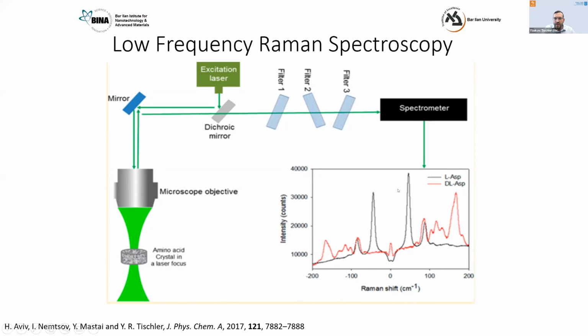For example, the L has this peak around 50 wave numbers, which is completely absent from the racemic mixture. And the way we understand that intuitively, we did some analysis as well, is that if you look at a chiral crystal, if it's entirely L or if it's entirely D, it's going to have one kind of packing on the nanoscale. But if you have the racemic mixture, those slight twists and turns in the chirality are going to